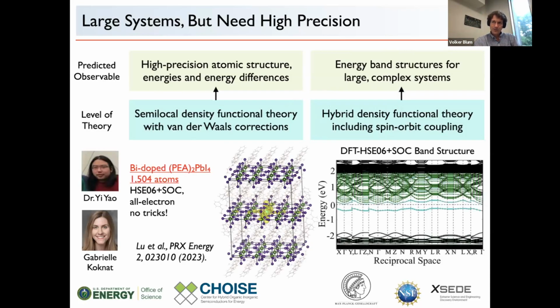And one thing we were hoping for was to see if we could get any electrons, free carriers, into the material by switching out a lead atom with an atom that's one proton heavier in the periodic table, so bismuth. That should bind an electron. And indeed, if you do a large enough supercell, 1500 atoms in this case, we can also go larger, as you saw earlier, and you run an HSE calculation with spin-orbit coupling, and there are no tricks here.